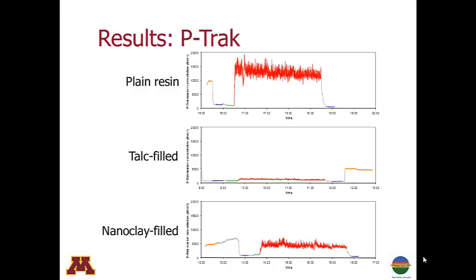The figures are color-coded. The orange data represent the particle concentrations in the room during a period when the enclosure door was open and we pulled room air directly into the apparatus using the fan unit. The blue data are background concentrations after we shut the enclosure door and air entered the apparatus through the HEPA filter. The green data are the background concentrations when the enclosure door was shut and the granulator was turned on with no plaques being shredded. We will primarily look at the red data, which were taken over 2 hours when the test plaques were being shredded. So, on this page, we are looking at the particle number concentrations measured over time using the P-Trak.